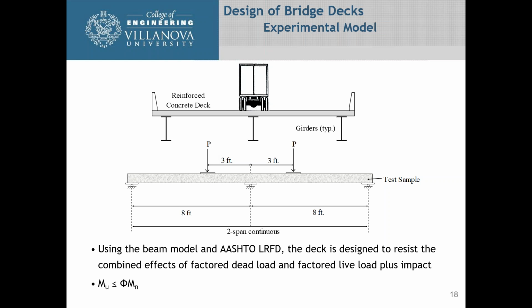So the way we modeled it was to have 2 wheel loads 6 feet apart, which is what AASHTO requires, and we're centering it on the middle support. And what we were doing with this research was looking at the effects of the truck in negative bending over the supports. So based on this, this is how we loaded it, and we go back to that: the Mu has to be less than phi Mn, where Mu is the applied load, and that has to be less than the capacity.